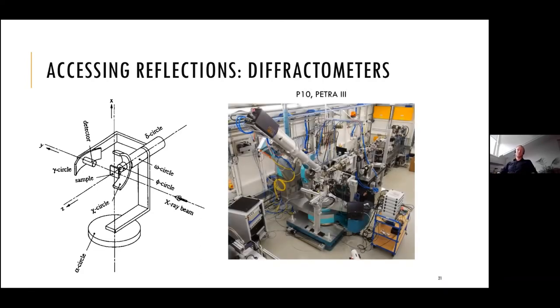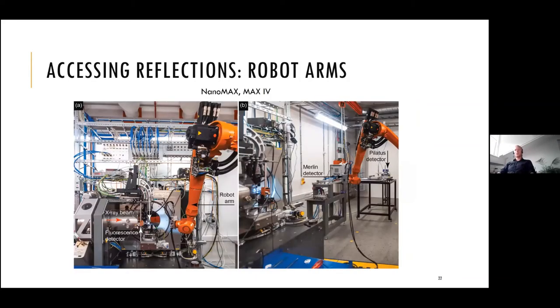As an example, this is how the actual diffractometer at P10 at the Petra 3 synchrotron looks like. It allows you to go anywhere in the full quadrant of the 3D space and access any reflection or orientation of your sample as you like. And of course, the good scanners, you need to precisely move your sample. Another option is to use robot arms. This is the case of NanoMAX at MAX IV here in Lund, where the detector is mounted on a robot arm, computationally moving. So it's programmed to move around the Ewald sphere, around the sample, and keeping the same distance. So it's very nice, and it gives much more flexibility in the measurements.